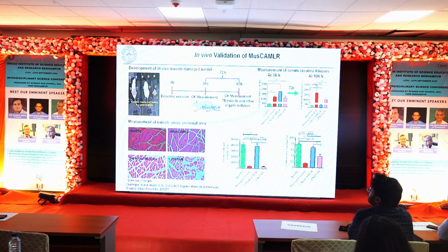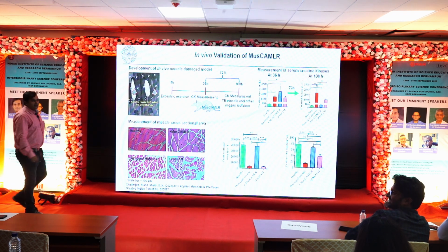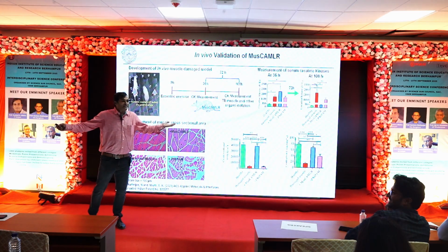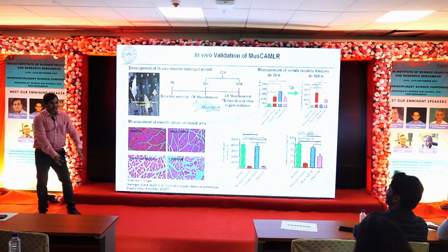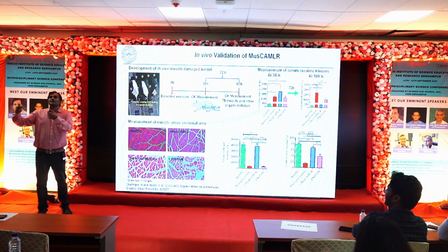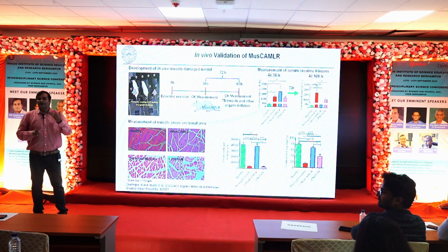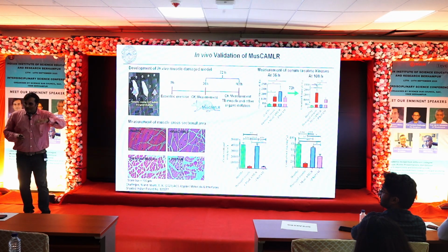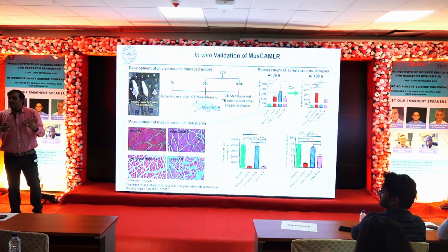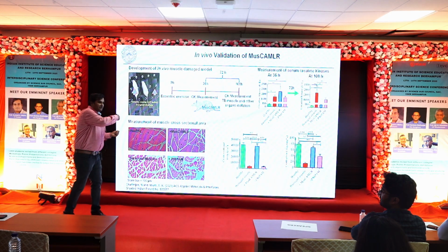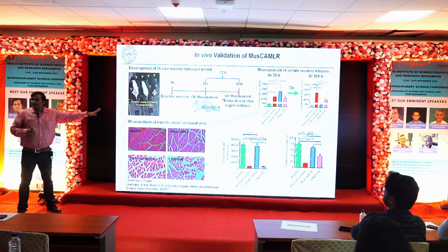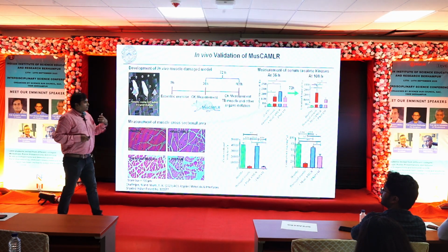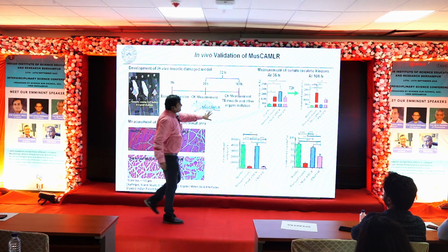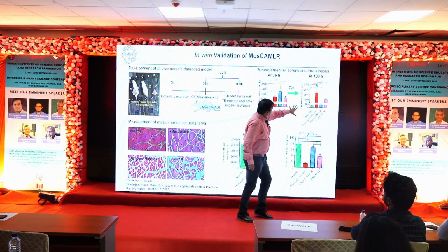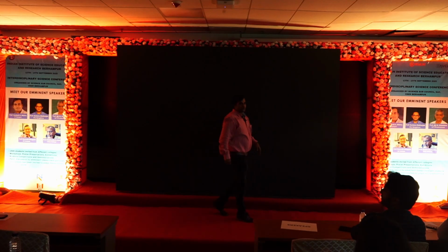So you can see these rats are running on the treadmill, okay, and we are cruel people, so we make them run for 40-50 minutes and they break their muscles, and then we do some investigation, biochemical analysis, collect their blood, find out what is their creatinine level, and it goes up, which gives the indication that there are broken muscles. And then we injected these animals with our generated hydrogel system. We found that within 3 days there was significant recovery, and here you see after 72 hours the biochemical parameter has gone down and creatinine has also gone down.